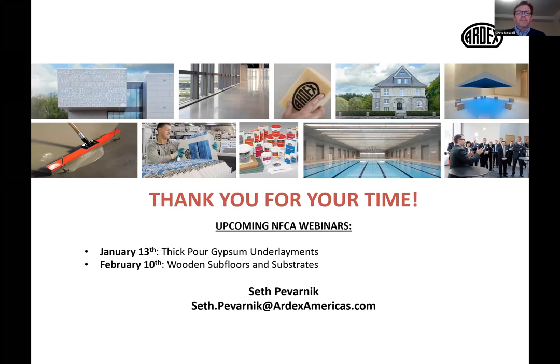That's great. Absorbency. I see absorbency as being a much bigger problem than people actually realize. They think maybe we've got moisture issues out there, but absorbency of over-densified concrete, compounded by the addition of fly ash, which, as you've mentioned, is increasing that density, and the inability of adhesives to get into the concrete, into the fissures of the concrete or the capillary action.